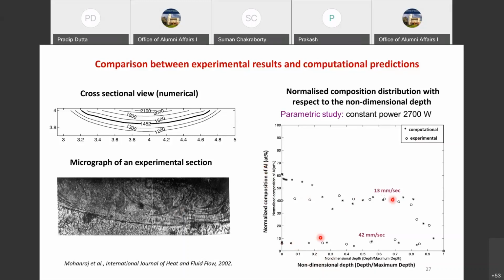This is at a certain speed, at a lower speed. Of course, the weld pool depth will also be more. This is the non-dimensional depth, so that we normalize it with respect to the depth of the pool. And along the depth from the top to the bottom, we see that these star ones are the computational, the circles are the experimental, and there's a reasonable match as far as the distribution of the species is concerned. And at the higher speed, of course, there is also a good match, but the depth is much smaller over there, and the normalized composition of aluminum is also lower, as we see here.